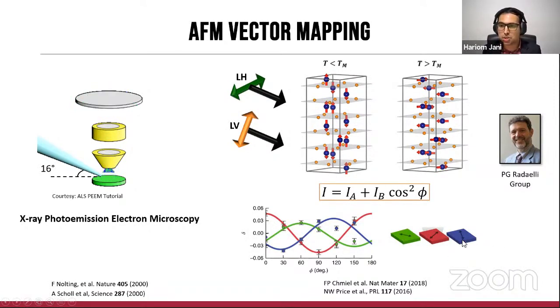Now, I've very simply shown here three cases because Fe2O3 has a trigonal structure, and predominantly you have three 120-degree separated domains, and they are time-reversed components. And as you can see here, this is obtained by fitting the linear dichroism value as a function of the overall evolution of the angle between the X-ray polarization as well as the local Néel order, which is captured here as phi. And by fitting this simple approximation, we would actually be able to get the local phase of every particular pixel that we're looking at, and thereby reconstruct, in some sense, a vector map of the antiferromagnetic order at the nanoscale dimensions.